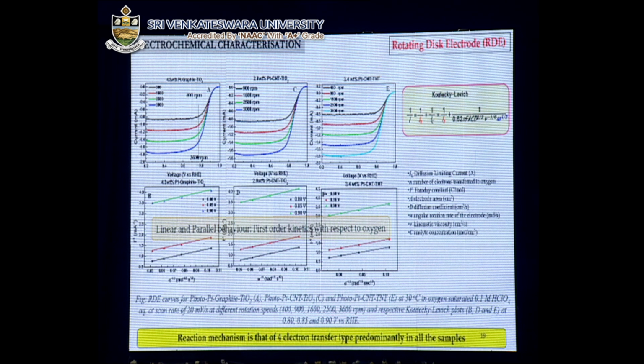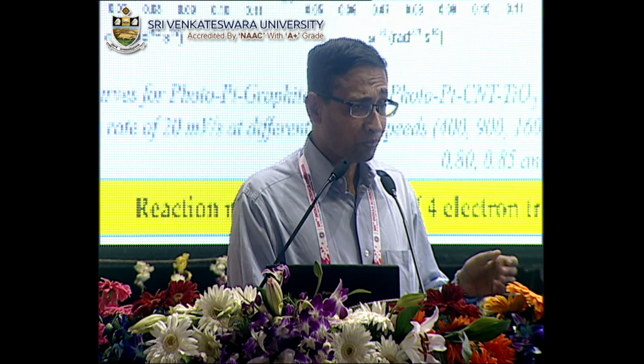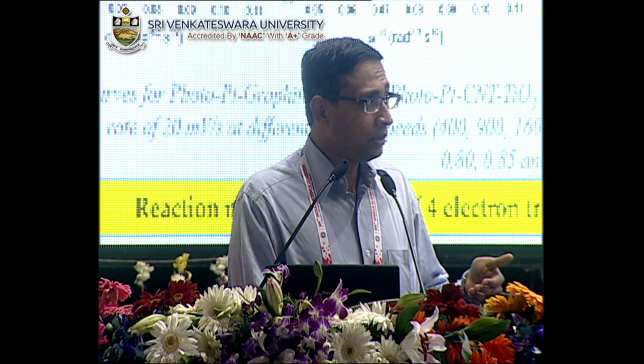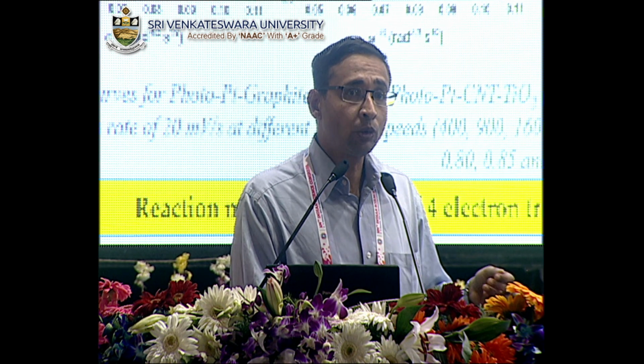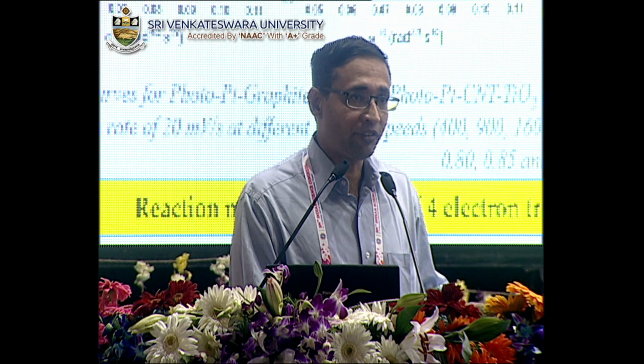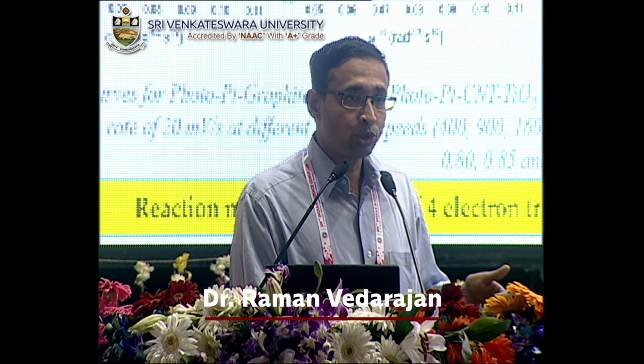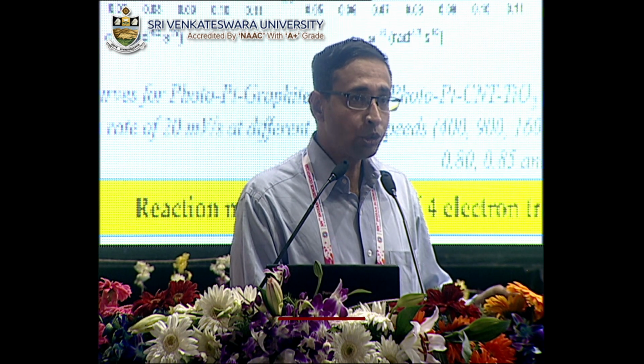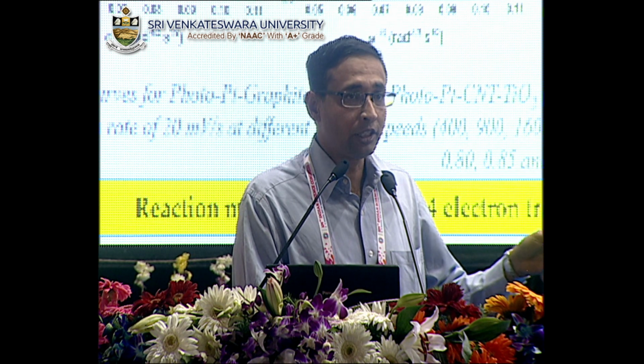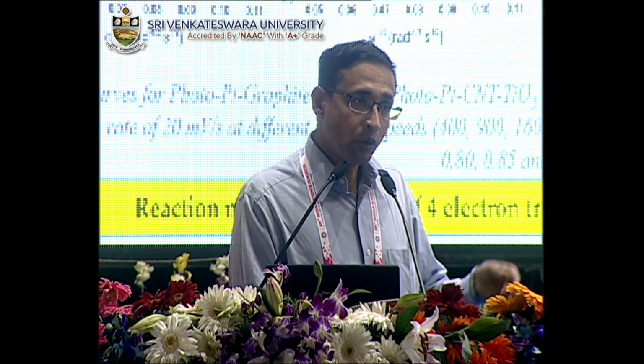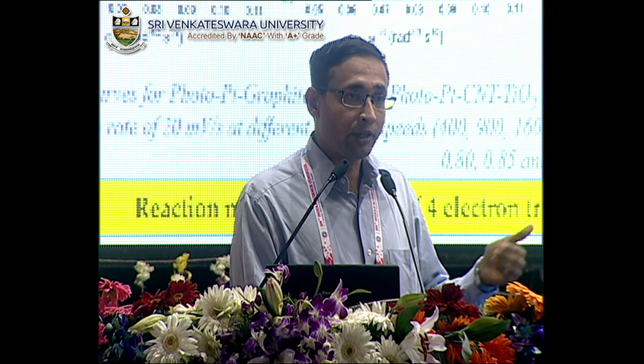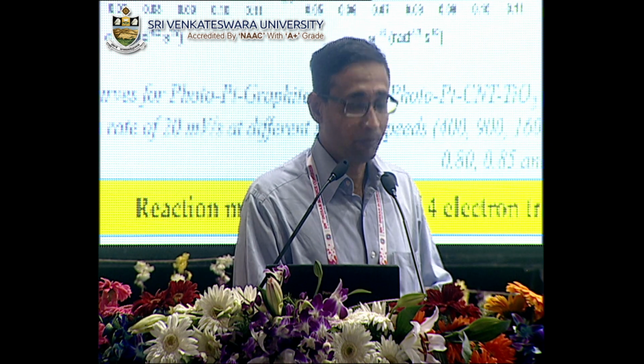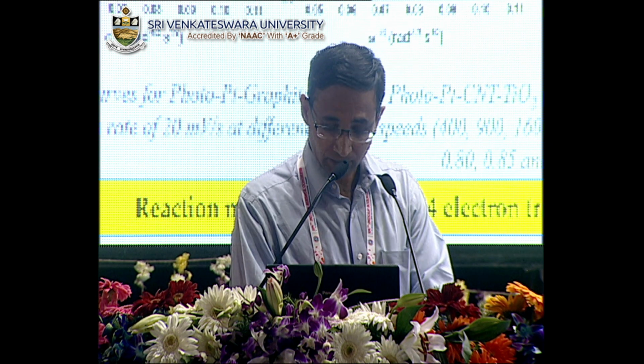We found that all these materials which we prepared undergo a 4-electron transfer mechanism, which is the most effective way in which the reaction can take place in a fuel cell. For example, when an electrocatalyst does not work properly, it undergoes a 2-electron transfer process, which is not efficient and leads to a lot of other byproducts. Whereas when it goes through the 4-electron transfer, which is proved by this technique, we see that the material, though it has very little platinum, can undergo the 4-electron transfer, which substantiates the previous results.